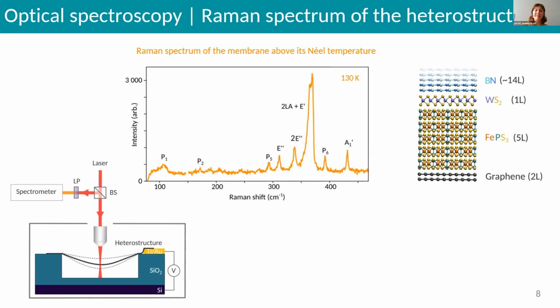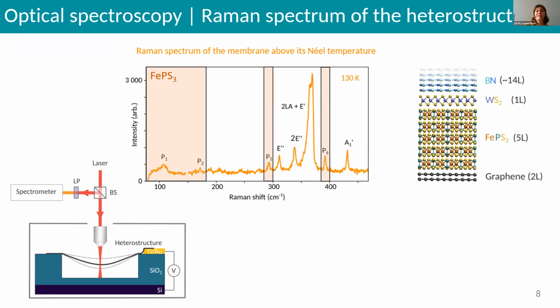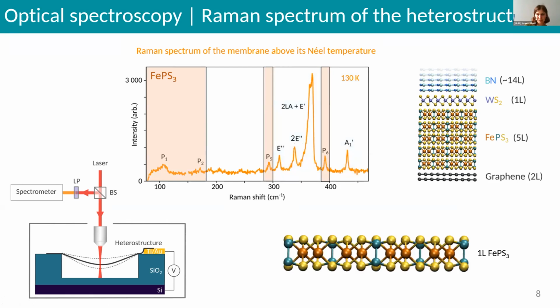Since we have more than one material in the heterostructure, we have peaks originating from FePS3, which we are interested in, but also from WS2. We will not care about these peaks, but only about the ones of FePS3. And even then, we have some distinctions. We have these two peaks that arise from the vibration of the bipyramid P2S6, and we have P1 and P2 that arise from vibrations involving iron atoms. And since it is the iron atoms that bear the magnetic order in FePS3, we will look in priority at these peaks.